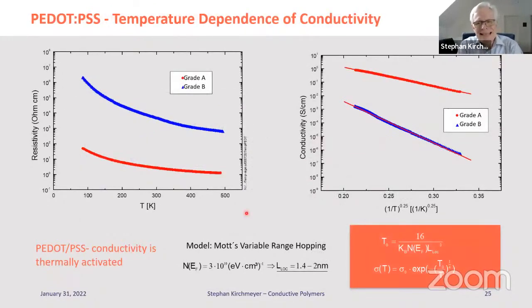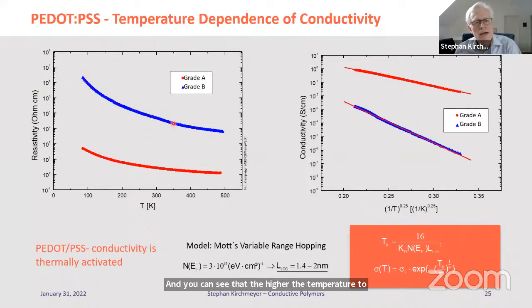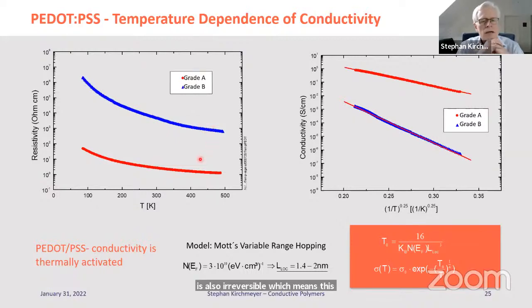Second, we can see this effect of the energy barriers between these particles by looking at the temperature dependence of conductivity. And you can see that the higher the temperature, the lower the resistance, meaning the higher the conductivity. And interestingly, up to a certain temperature this is reversible, but starting from a certain temperature, this is also irreversible, which means this effect of rearrangement does not only take place with a certain solvent, it also takes place just at a certain temperature.